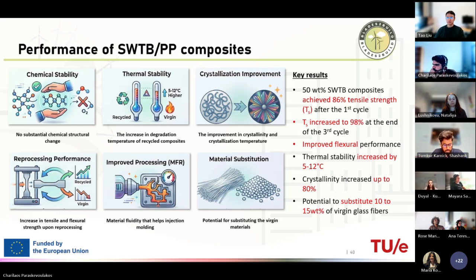And also, we wanted to assess the thermal performance of these materials, where we found out that the recycled materials coming from wind turbine blade waste actually helps the composite to have good thermal stability. That is, the degradation temperature has actually increased by around 5 to 12 degrees Celsius for these recycled composites.